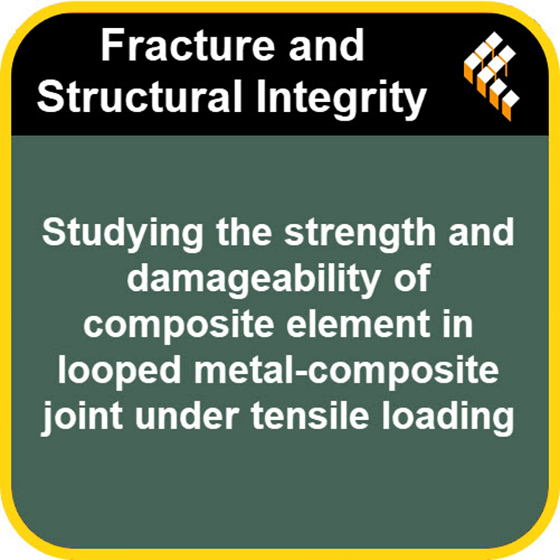Extrusion, like it was squeezed out. Literally squeezed out. The epoxy resin was being pushed out from between the fibers in that zone of maximum compression where it contacts the metal part. Like squeezing water from a sponge. That's a good analogy. They actually measured a little ridge protrusion about 0.17 millimeters high and half a millimeter wide at that maximum 300 kilonewton load. It just shows how dynamic things are. Even the matrix material is moving.